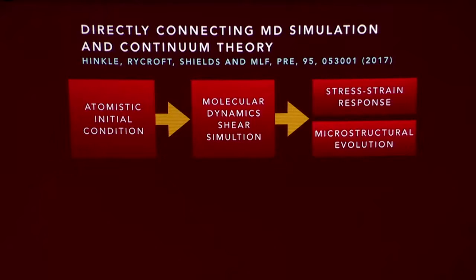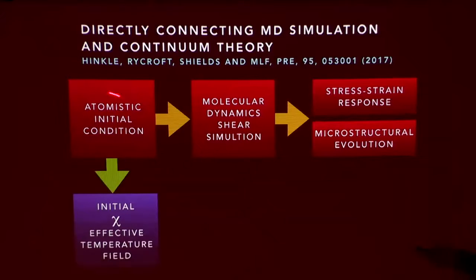I'll show you that in a second. And then what I'm going to want to do is take that atomistic initial condition and use it to create an effective temperature field. So I have a different effective structural temperature at different locations in the material. Some places are more disordered, some places are less disordered. I can measure that through the potential energy per atom.